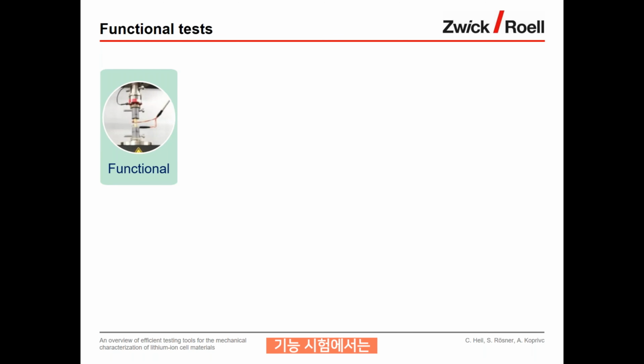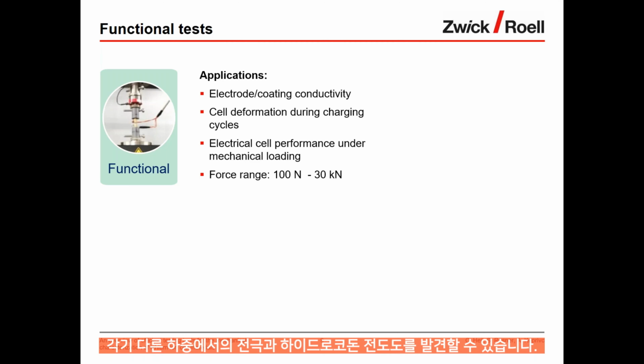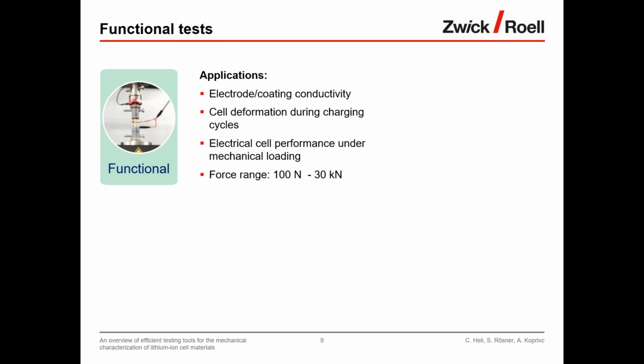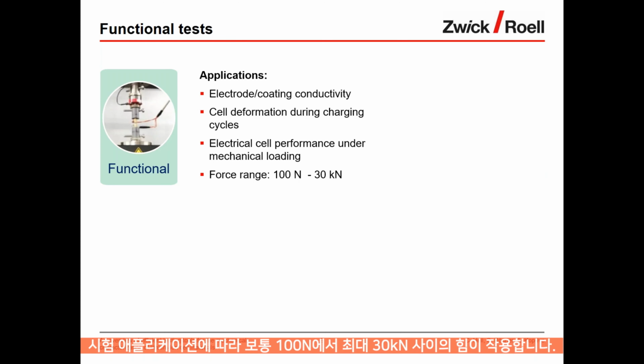Looking at the functional tests, here we look at electrode and electrode coating conductivity under different loads. We look at cell deformation during charging cycles. We look at electrical cell performance under mechanical loading. And here typically we also see force ranges between 100 newtons and up to 30 kilonewtons depending on the test application.